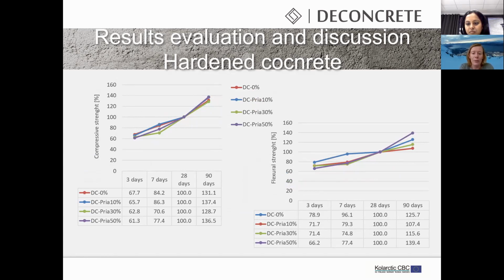Furthermore, the impact of the supplementary cementitious materials on the development of strength. It is visible that there is a delay of the hardening from a reference mix. So I put as a reference the 28-day strength, and then there was a slower development of strength for 3 and 7 days of the mixes with a high replacement ratio, but there was a higher gain after 90 days. So there is an obvious effect of addition of the supplementary cementitious material in the long term, and it's not achieved after 28 days.